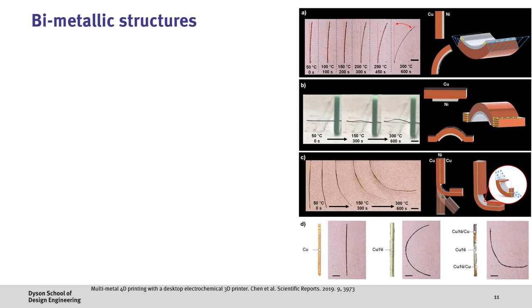Now with this ability to print in multiple materials, this allows us to make bimetallic structures which, if we intelligently place the material, allows us to have thermally responsive materials. In the first case, you can see with a bimetallic structure, since the thermal expansion coefficient of copper is higher than that of nickel, this causes a bending in the structure when heated. And depending on where the material is deposited, we can achieve a range of different motions. In this example, we create self-assembling structures with the letters ICL.